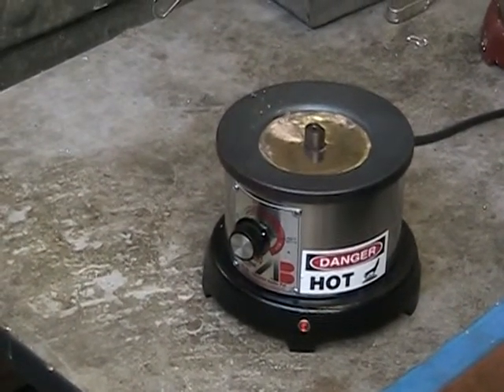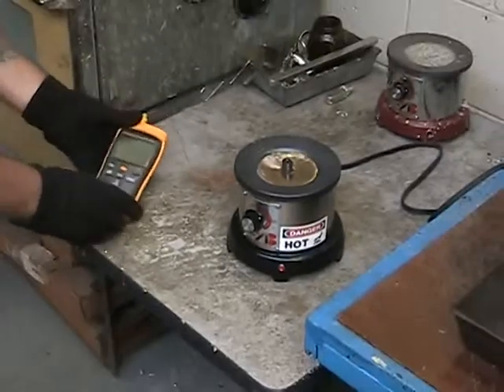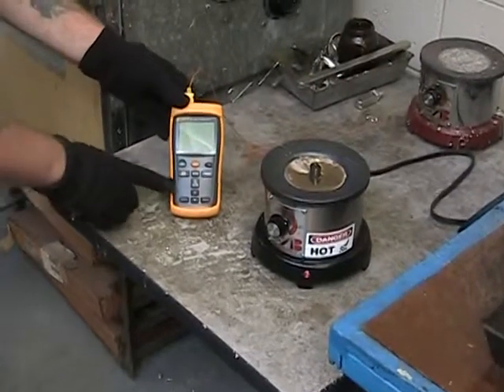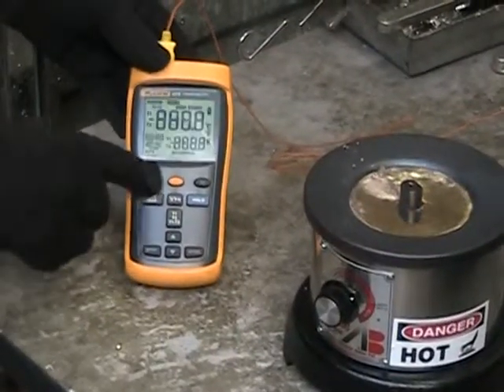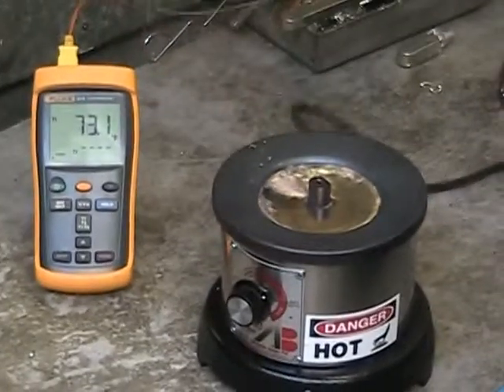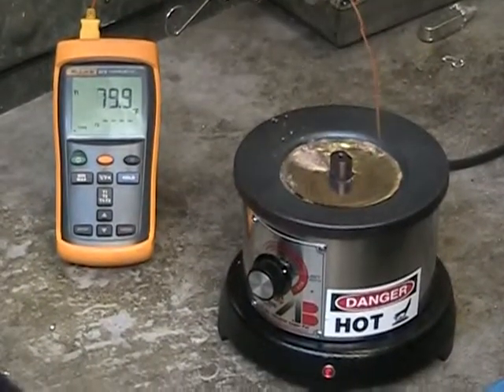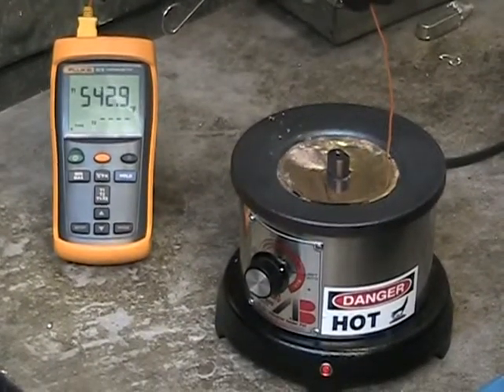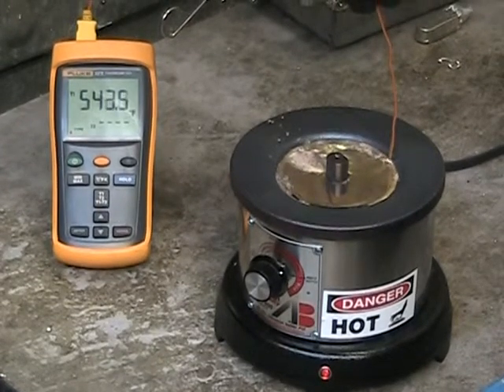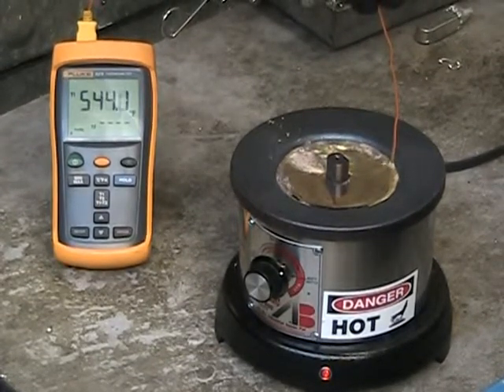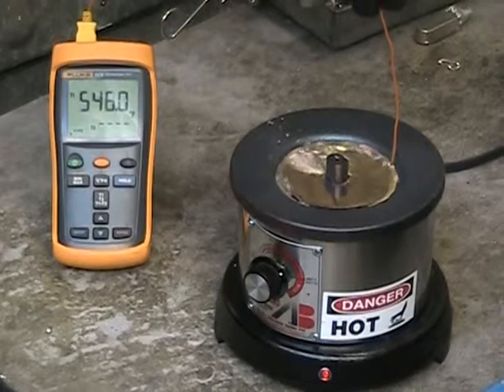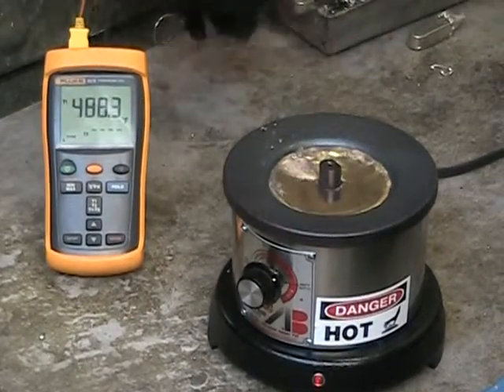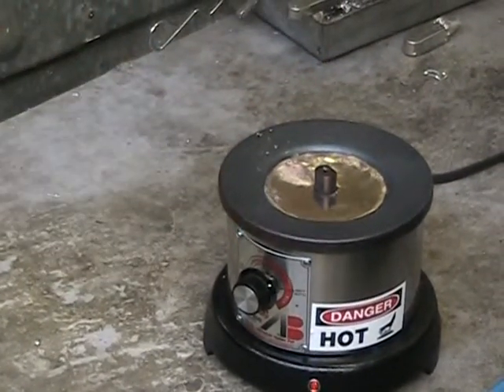To determine the actual temperature of the solder in the pot, you will need an independent temperature sensing device like the digital meter shown. The thermocouple sensor should be placed near the crucible wall, approximately 1/2 inch below the surface of the solder. The run light will turn off and on once the pot begins to idle around the set temperature. The operating temperature could then be adjusted by turning the knob clockwise to raise it and counterclockwise to lower it. All surfaces and components, including the draw skimmer assembly and the knob, should be considered extremely hot during use.